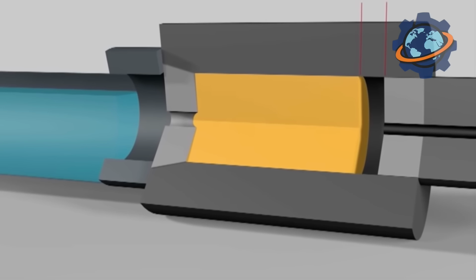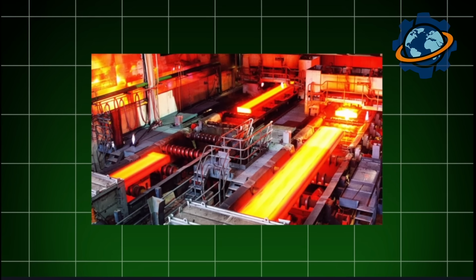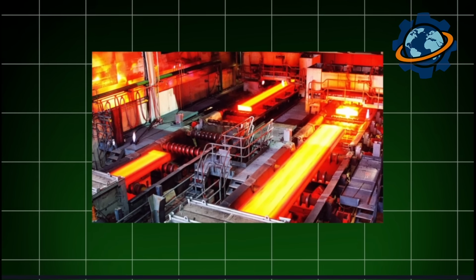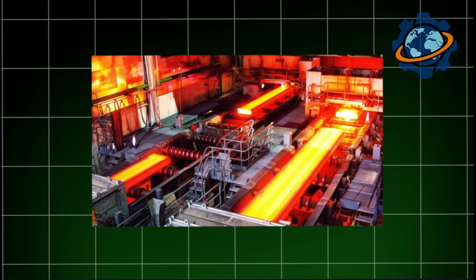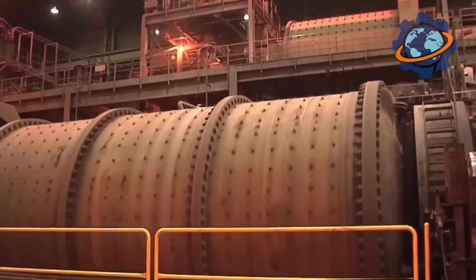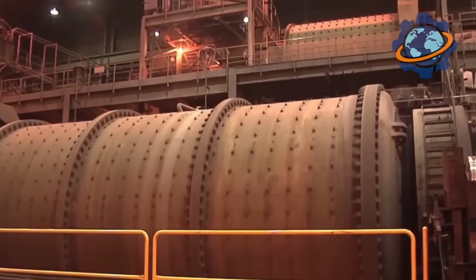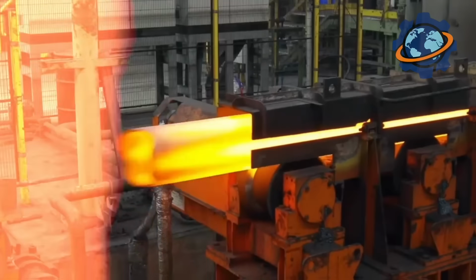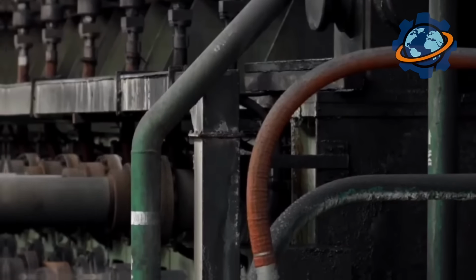The slab gets thinner and longer. It passes through the next pair of rolls. Even thinner. Dozens of times. An 8-inch thick slab becomes a sheet 1 to 2 millimeters thick. Length grows from 33 feet to over half a mile. Rolling speed on finishing mills reaches 50 miles per hour.